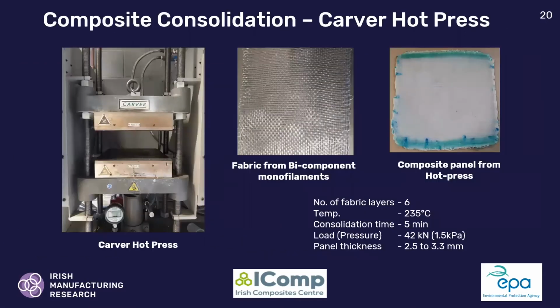Now the next stage is to develop composites using this fabric, which is carried out at the University of Limerick using a Carver press. We use 6 layers of this fabric. The temperature is 235 degrees Celsius. The consolidation time is 5 minutes with water cooling, and the load is 42 kilonewton. The pressure is 1.5 kilopascal. The consolidated panel thickness is 2.5 to 3.3.